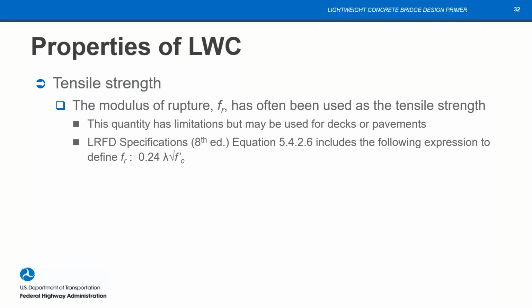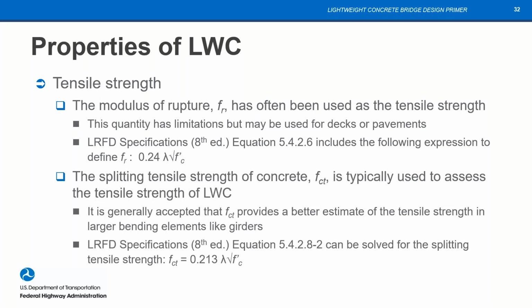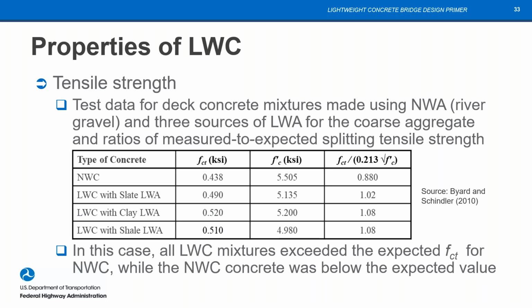As far as tensile strengths, modulus of rupture is often used as the indication of tensile strength. But what we find is that instead for lightweight concrete, we typically specify the splitting tensile strength of lightweight concrete. One thing that you do see is we have a concrete density modification factor, the lambda term, that's now finally, well, back in 2015, it was added into the specs. Prior to that, it was simply stated in text prior to the equation, but now the lambda has been added into all the equations where it belongs. So I would encourage, if you're looking at tensile strength, that you would use the splitting tensile strength rather than the modulus of rupture. Here's some example of some data on tensile strength for lightweight concrete.